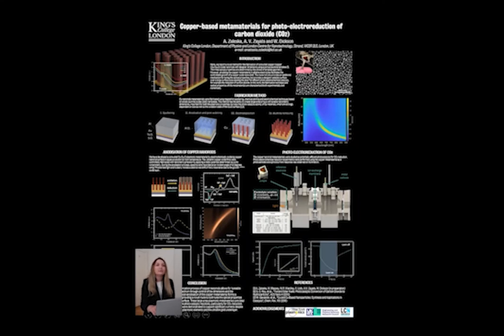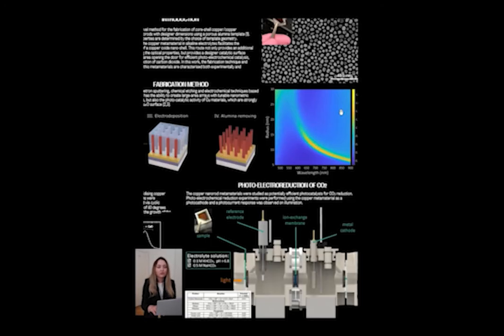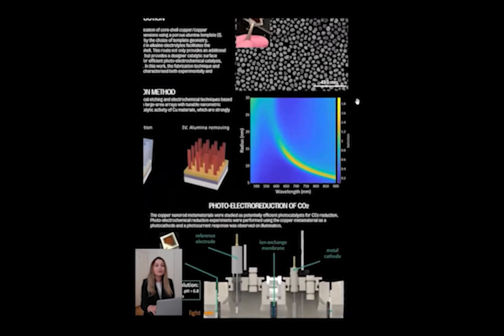Our fabrication method is highly controllable and can be easily applied to large surface areas with an added benefit of high uniformity. Copper as a material has a lot of advantages, such as high natural abundance and low cost, that makes this material very attractive for commercial exploitation. But also, copper nanorod metamaterials have a strong tunable plasmonic response. In principle, by changing, for example, the radius of rods, the plasmonic resonance can be tuned to catalyze chemical reactions that occur on the highly reactive surface of copper nanomaterials.